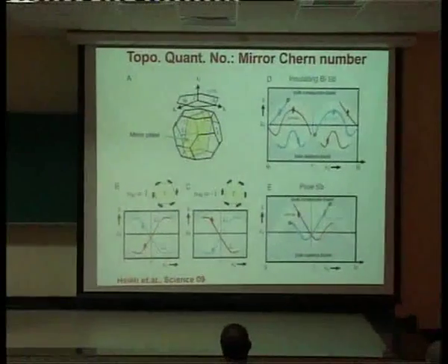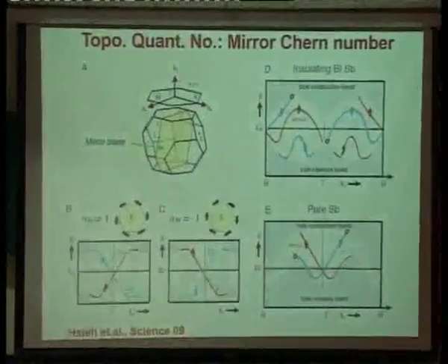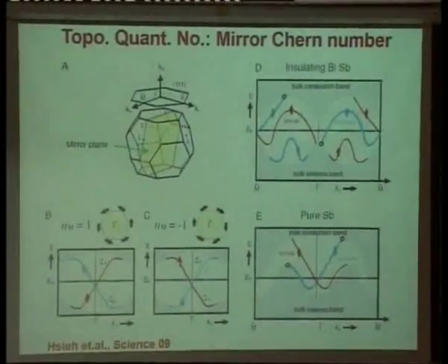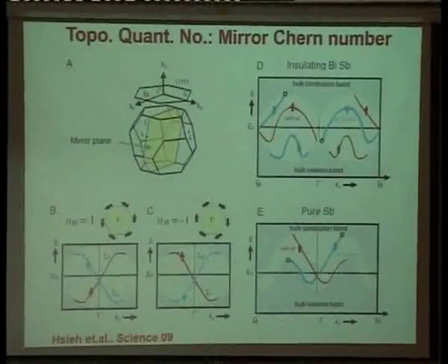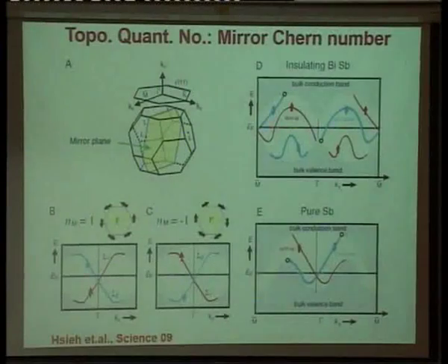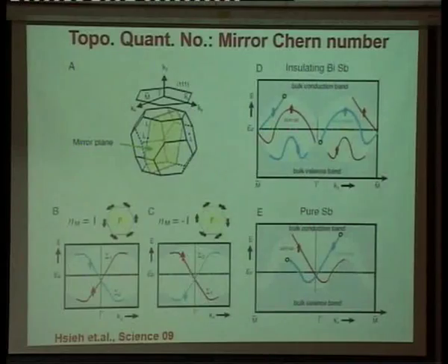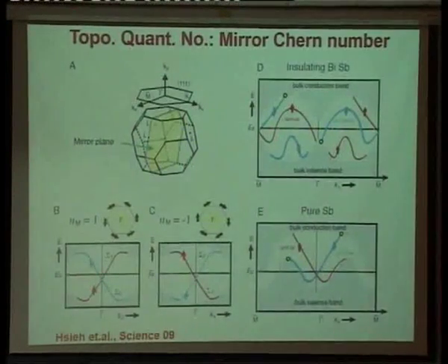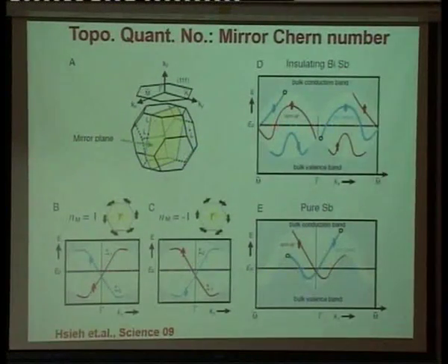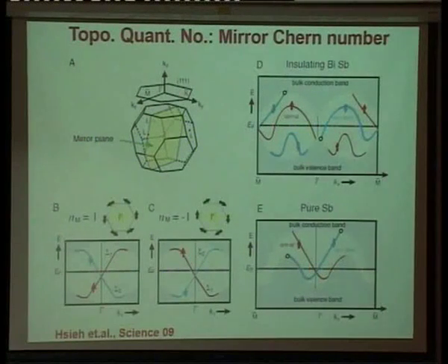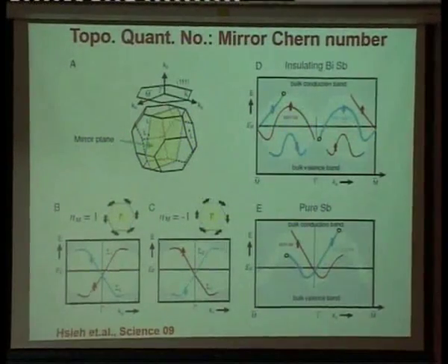Another interesting thing about 3D topological insulators is that you have an additional Chern number, like the mirror Chern number that's tied to this chirality. I'll not get into that, but just remind you that we determine it experimentally because it will come up. It will be important when we study topological insulators beyond Z2, which have unusual mirror Chern numbers. In the case we studied, it is -1. This is tied to the additional momentum space mirror plane.